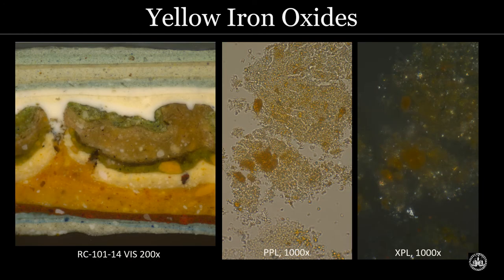So here are some examples of yellow ochre found in our building, some of my most memorable examples. So here we have another sample from the Robert Carter House, which had a few yellow ochre pigments. It had this early, very, very deep, intense yellow paint, which contained yellow ochre as well as white lead and even some red lead, which has a bright reddish orange color, which really would have intensified this yellow. And then later on, we see more large, coarse particles of yellow ochre used to make this olive green paint. So here it was mixed with a blue pigment called Prussian blue.